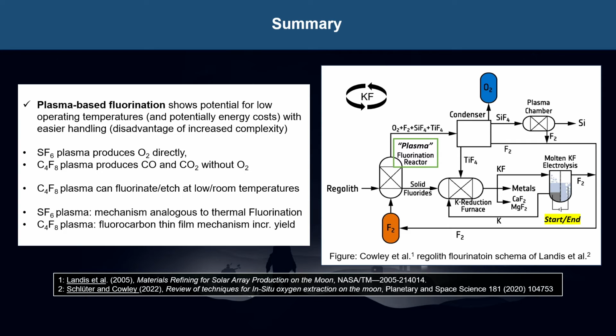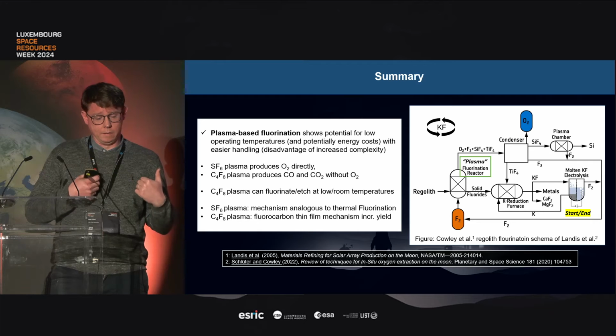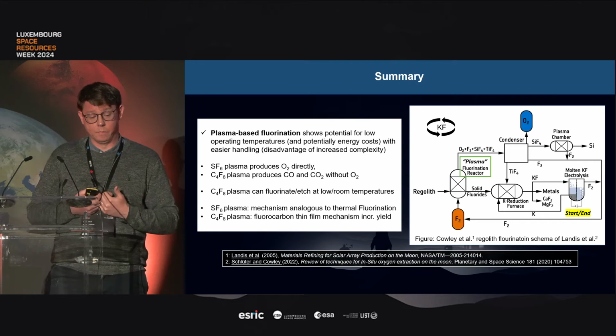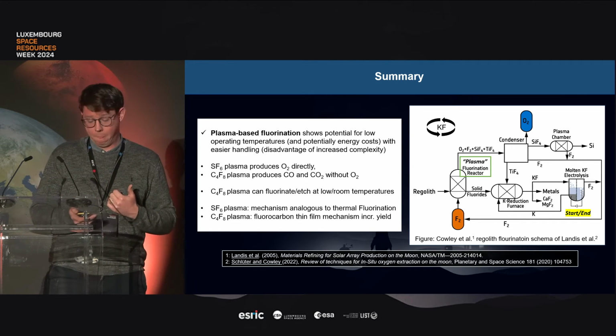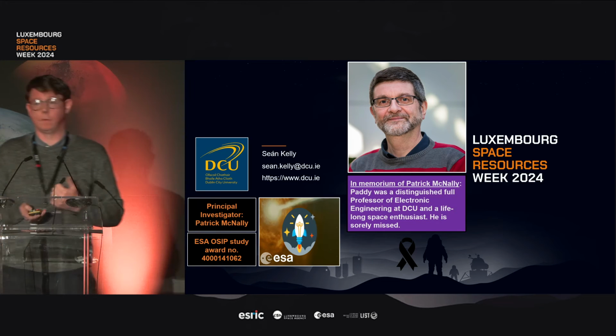What we found in summary is that the sulfur-containing plasma, the SF6, produces O2 directly. The fluorocarbon gas, C4F8, produces CO and CO2 without oxygen. We also saw that we didn't need to heat the plate where the regolith was with the C4F8 plasma, so it can do this at room temperature. The mechanism for SF6 appears to be analogous to thermal fluorination, while the C4F8 is giving a novel mechanism involving thin film formation. So, yeah, thanks for your time. Cheers.